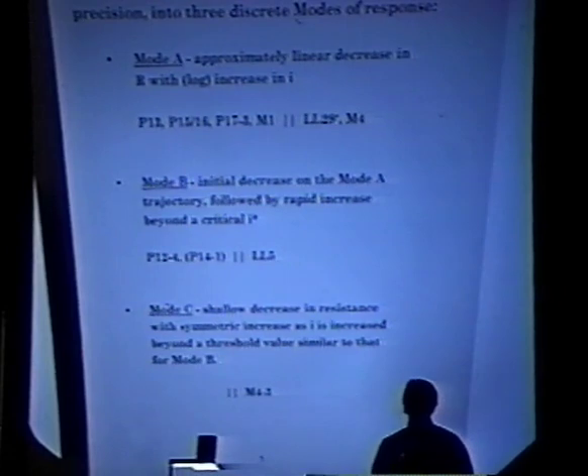The third mode is a shallow decrease and increase in resistance. This is a cathode that really doesn't have any capacity to load, probably because the interface is in some way damaged electrochemically, or the electrolyte conditions are simply not conducive to good loading. I can show you the breakout of data into those three groups.